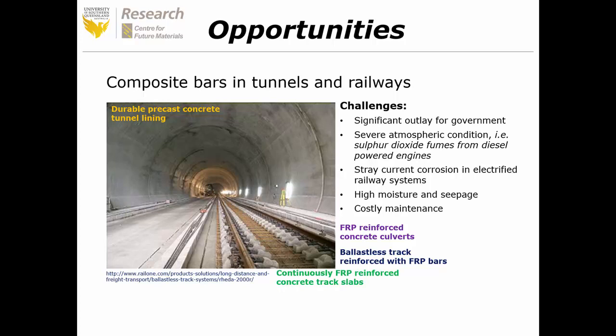In railway tunnels, reinforcing bars are prone to corrosion because of the severe atmospheric conditions. For railway lines or tunnels where trains are operated by diesel-powered engines, the amount of sulfur dioxide emissions of this type of train is significant, increasing the probability of corrosion problems. Similarly, for electrified railway systems, stray current corrosion is a significant issue, but by using FRP bars, this issue can be eliminated.